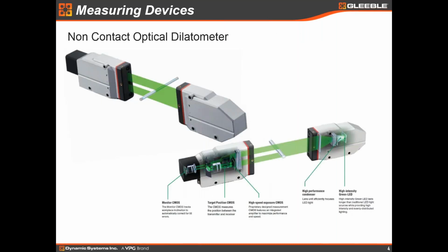I'll segue here a moment into talking about a couple of the ways that we measure the dilation of a sample in the Gleeble. This shows our non-contact optical dilatometer. This is a green LED light-based device that measures the diameter change of a metallic sample as we heat and cool it in the Gleeble.